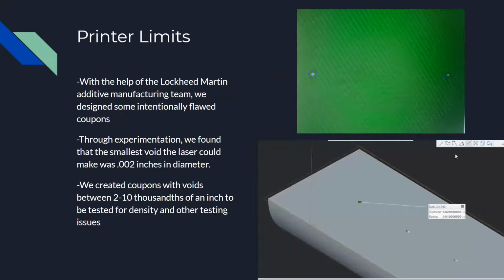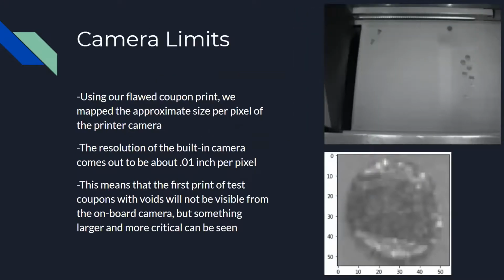We then needed to test the printer limits to see what intentional errors we could later introduce to see what errors we could detect. So we found that the printer has a minimum print size of 0.002 inches in diameter, and the camera, using our mapping, has about 0.01 inch per pixel, allowing us to know exactly how large of an error we can detect.